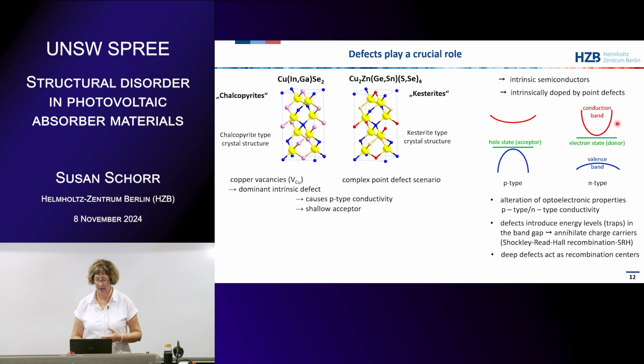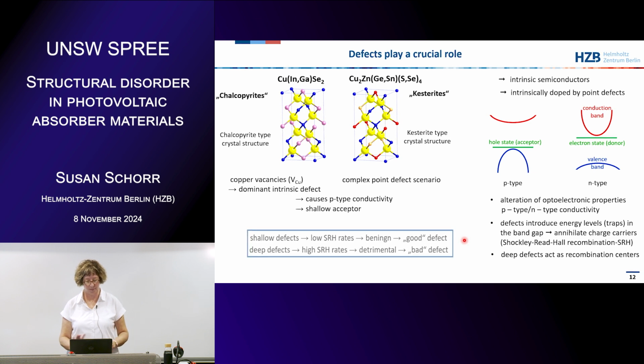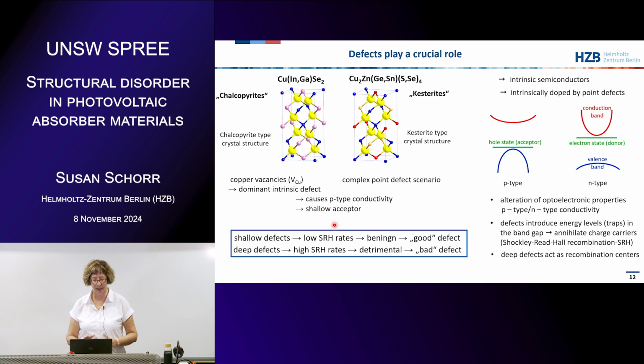That's fine. But the defects can also introduce deep levels in the band gap, not as shallow as I have shown here in the figure, but deeper. And then this defect acts as a recombination center for the charge carriers. This is called Shockley-Read-Hall recombination. And this is something you don't want to have in your solar cell, because you would like your charge carriers to reach your contacts so that you have a current flowing. So if we have shallow defects, then we have low Shockley-Read-Hall recombination rates, and these are the so-called good defects. The deep defects are the ones you don't want to have, because they are detrimental for the absorber, and these are so-called bad defects.